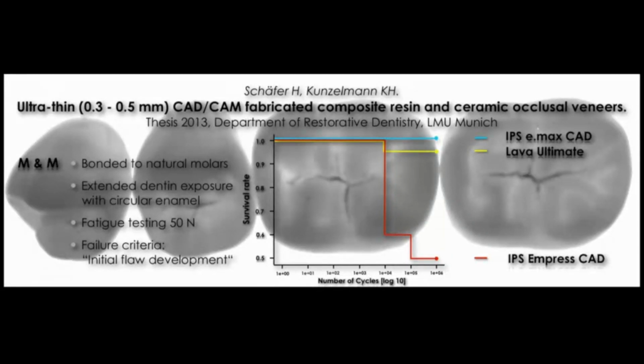Especially, the study of Schäfer and Kunzelmann from LMU Munich shows that we can thin it out depending on the substrate below. If it's enamel, you can thin it out much more in comparison to dentin support. So it depends strongly on the support available, and that makes sense. In other words, we probably, and we need clinical trials to confirm that, can use thinner occlusal veneers if we still have enamel available, because the elastic modulus is much higher, and we need thicker ones if dentin is exposed. It makes sense because it depends on the morphology of these teeth, of course.